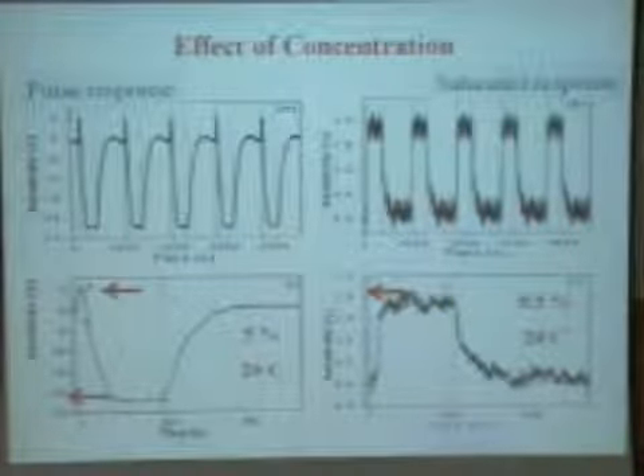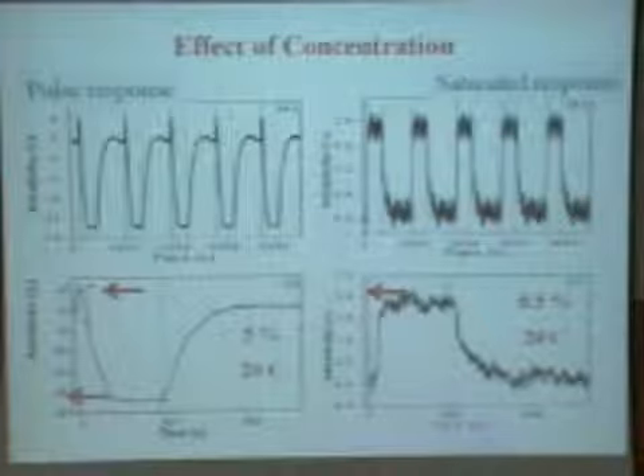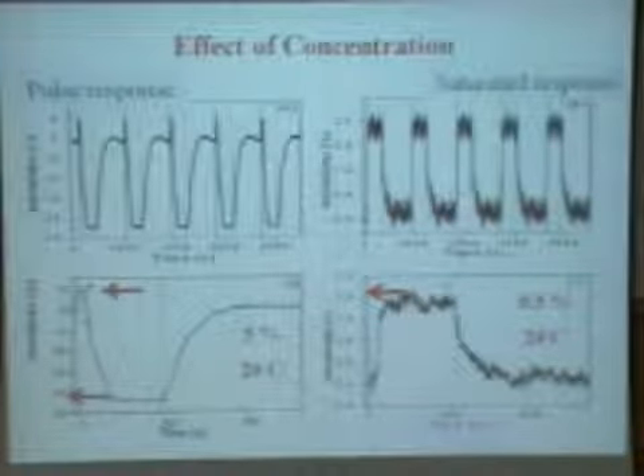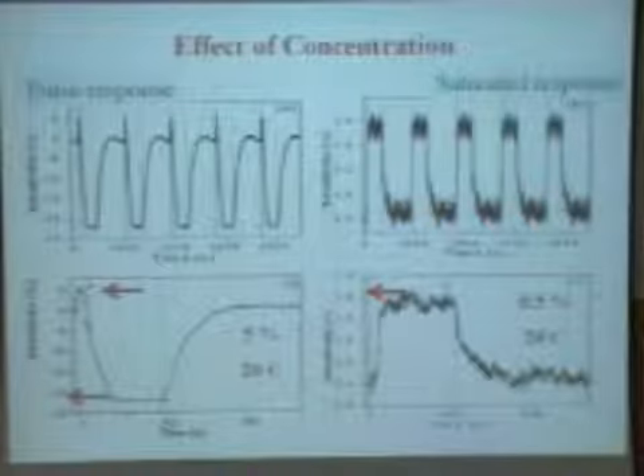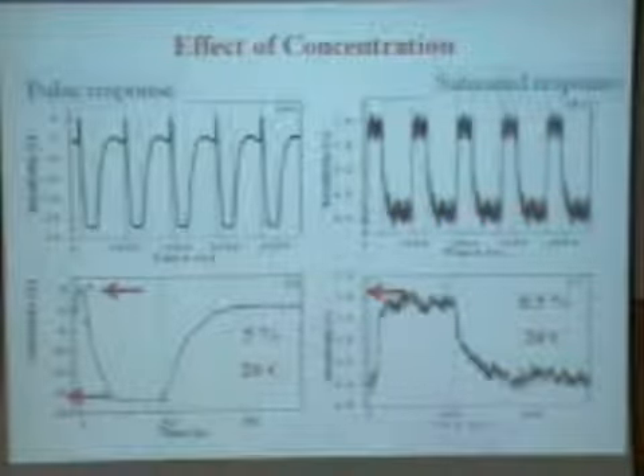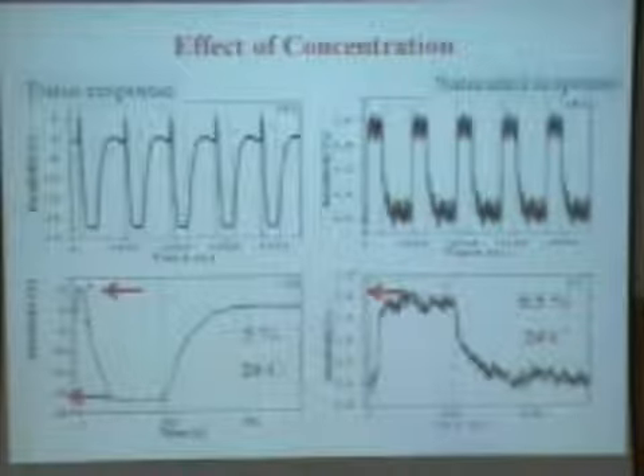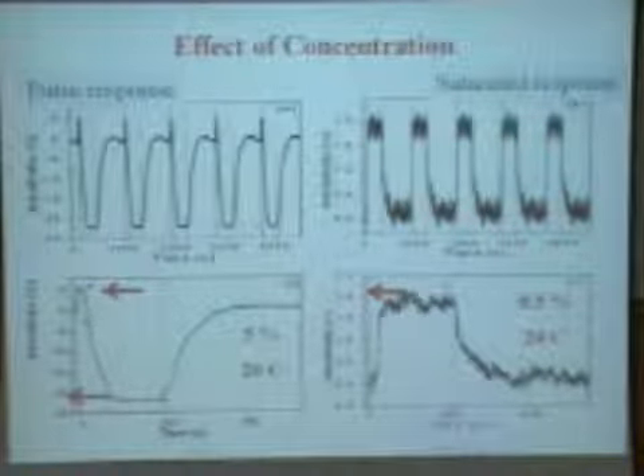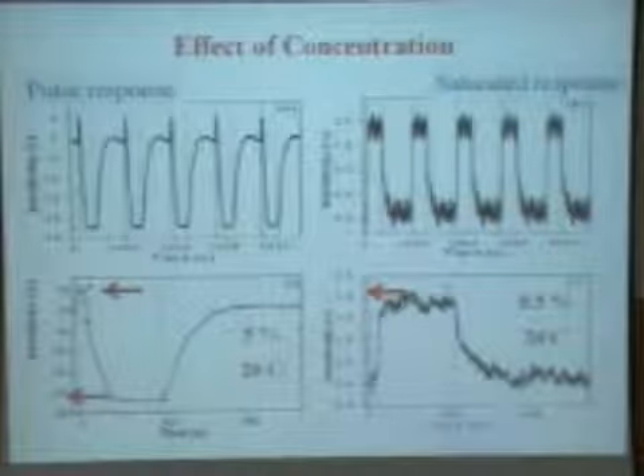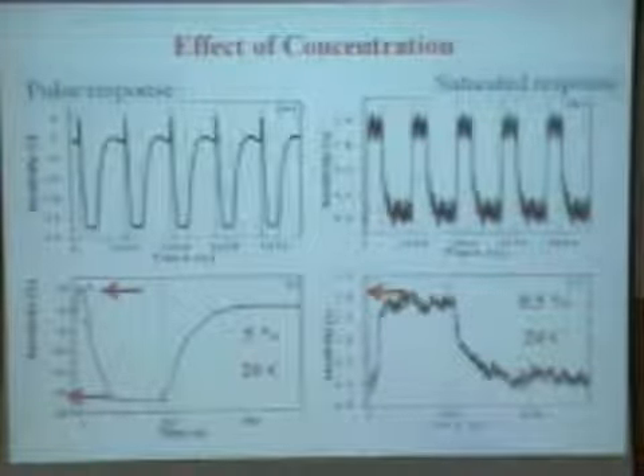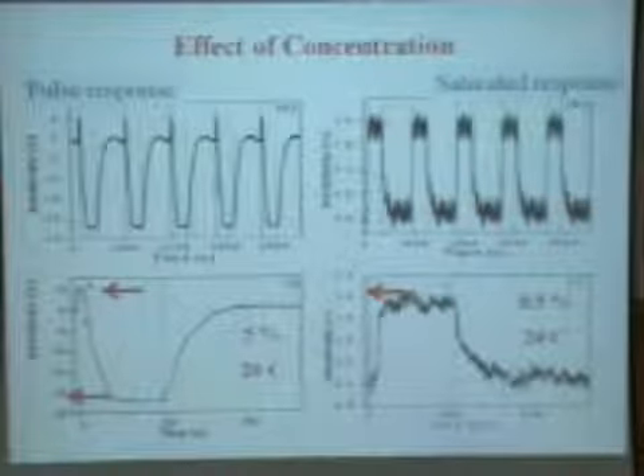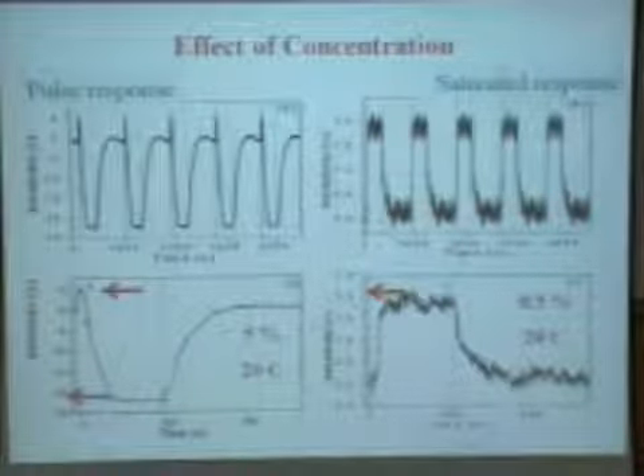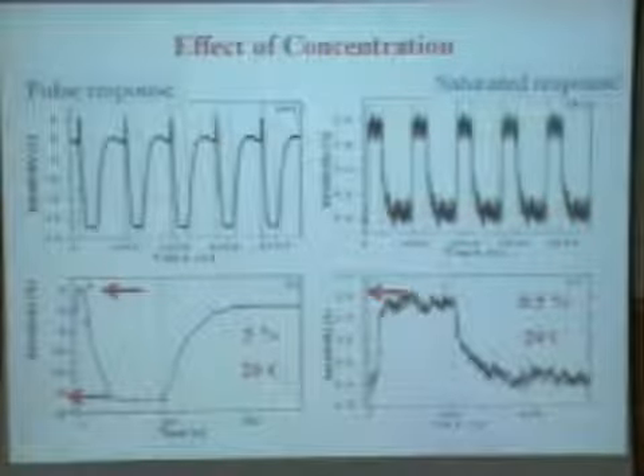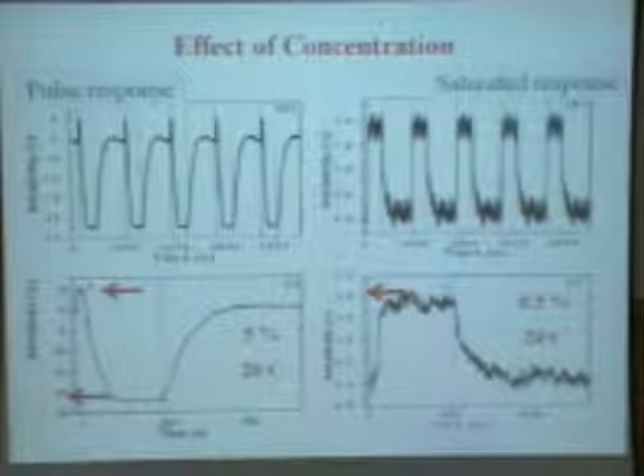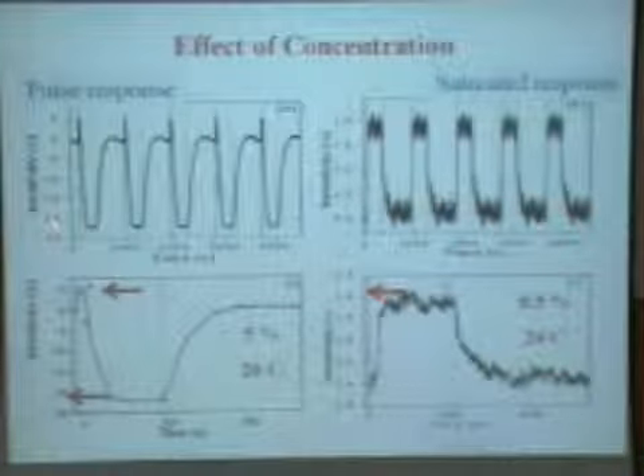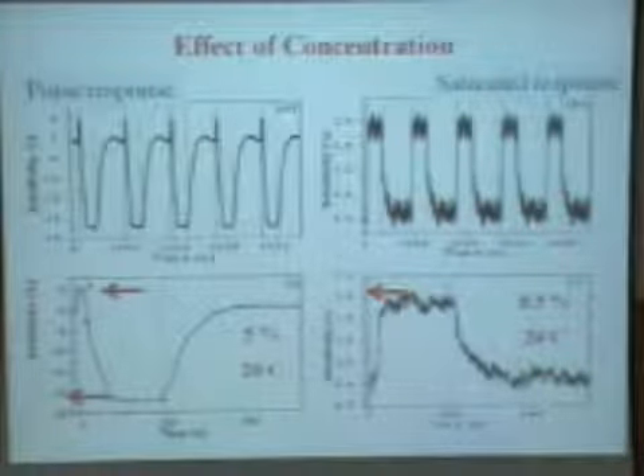When palladium goes to palladium hydride, a 4% lattice expansion takes place. The nanoparticle will expand. The hydrogen also acts like impurity scattering centers. So the crystal structure is expanding, and because of the scattering effect, the electrical resistance and the mobility get affected. So: physical adsorption, chemical adsorption, diffusion, incorporation into the lattice, expansion of the lattice, and change in the electrical properties. All these processes decide whether you will have a pulse-like response or a saturated response.